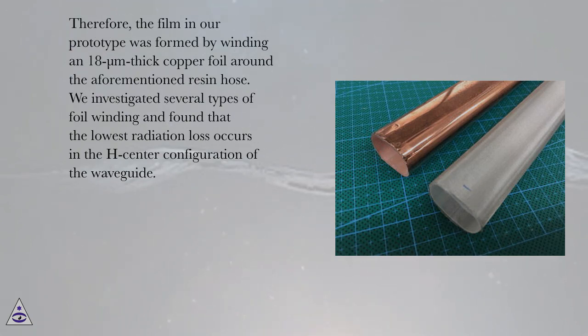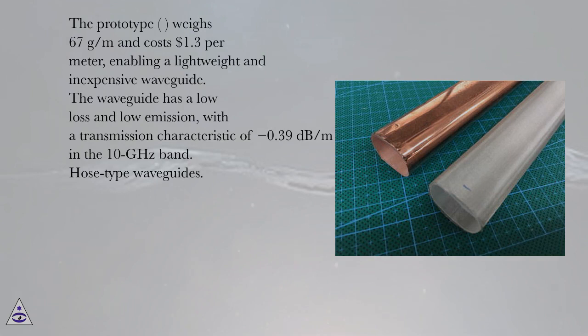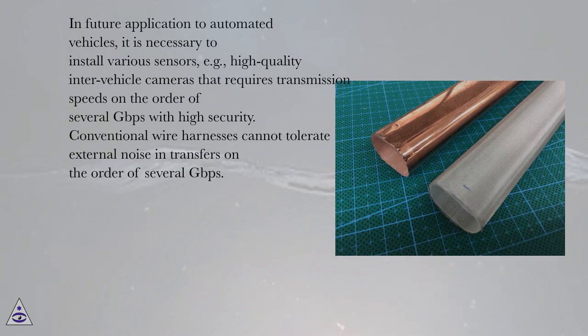hose. We investigated several types of foil winding and found that the lowest radiation loss occurs in the H-center configuration of the waveguide. The prototype weighs 67 grams/m and costs $1.30 per meter, enabling a lightweight and inexpensive waveguide. The waveguide has a low loss and low emission, with a transmission characteristic of -0.39 dB/m in the 10 GHz band.